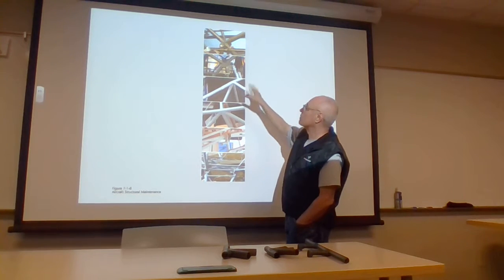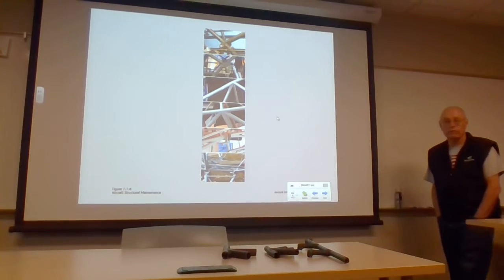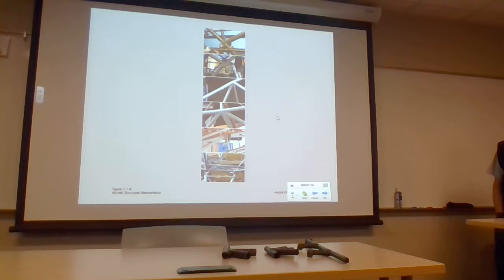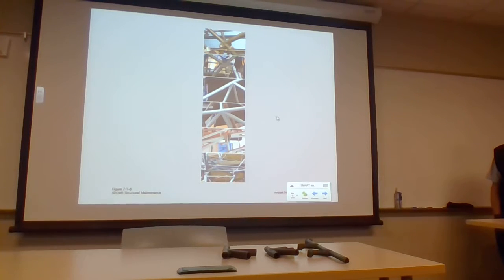You've got cluster welds that are used throughout the aircraft for some purposes. When aircraft fuselages have to be put together, usually they work in piece parts in a jig. So what they'll do is they'll tack up individual parts in a jig and then take it out of the jig and then complete the welding outside of it. That way they don't trap any of the stresses that would cause warpage.